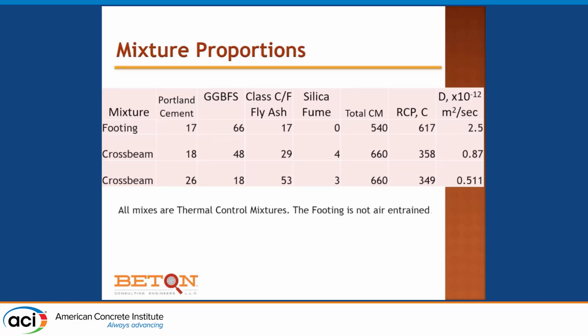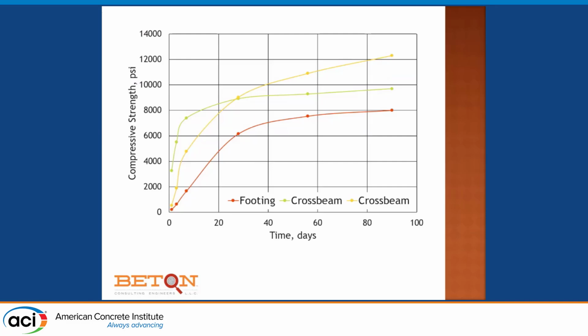You can see the diffusion coefficients are quite low, particularly for the silica fume containing mixtures. And no one wants to repair these structures, and besides there's the ambitious 100-year design life with no maintenance, so we had to design for that. And this is our compressive strength gain. You can see the footing has a 90-day strength, these are cylinders now, at about 8,000 psi. The cross beams, with additional silica fume and less Portland cement, were getting just under 10,000 at 90 days in the lab. But we're also getting 4,000 or 3,000 psi at 18 hours in the lab.